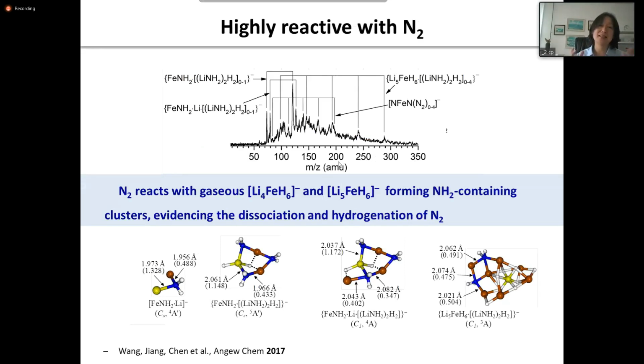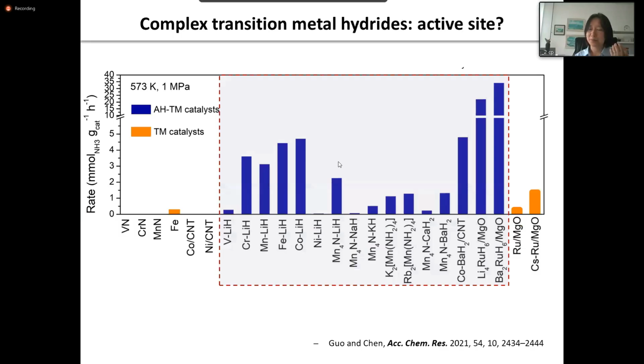phase. We notice that these gaseous phase species are highly reactive with dinitrogen. They can dissociate dinitrogen into an amine group, which means that dinitrogen can be dissociated and hydrogenated at the same time. So that investigation gives us a very strong idea that at the surface, even if in the bulk phase a ternary complex hydride cannot be formed thermodynamically, we probably have a high chance to form some complex hydride at the surface. And this complex hydride would have a unique role in catalyzed chemical transformation. So that's the information that we derived from the gas phase investigation.